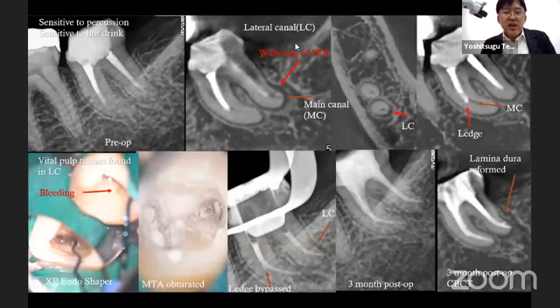Another case, here, this is a retreatment case. As you can see, you have a lateral canal. The CBCT here shows the lateral canal. And you see the curvature here, more than 40 degrees. I'm sorry, I didn't use the TCA technique in this case. I used the rotating shaper at 2000 RPM to reach the working length. And this is a post-op. Of course, I obturated the canals with MTA. Here, you see the lateral canal filled with MTA. And these are 3 months post-op CBCT images showing nice periapical healing compared to the pre-op radiographs and the CBCT images.